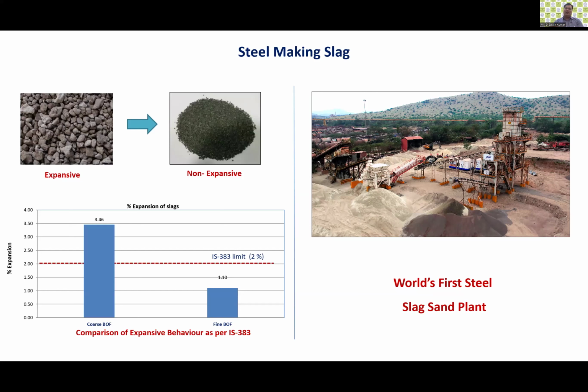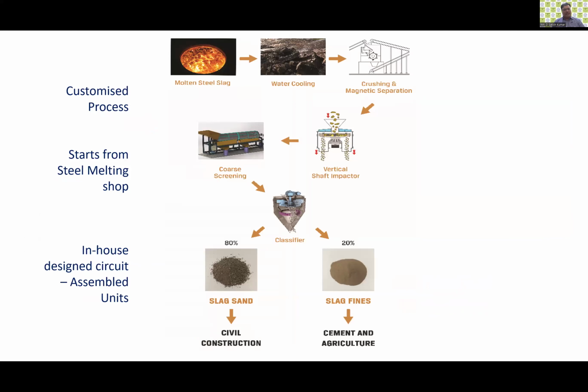The process has been developed in such a way that those fines are being sucked and removed, and that's how the world's first steel slag sand plant has been established at JSW Vijayanagar Works, where we started converting our steel slag into steel slag sand from this unit. This process is a little different than what used to make sand from our iron making process, where the fines was not an issue. Here, the fines was a bigger issue. So we have adopted a dry classifier where the fines were sucked, removed, and that's how we get two different products out of this whole process.